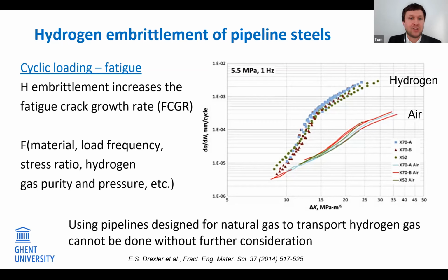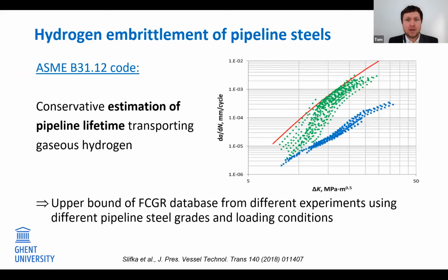Well, using pipelines designed for natural gas, which are used nowadays in the existing grid, to transport hydrogen gas in the future cannot be done without further consideration. The pipeline lifetime can be estimated conservatively by using the upper bound of the fatigue crack growth rate database, gathered from experiments using different pipeline steels, grades, and loading conditions. This method is proposed in a recent modification of the ASME code B31.12, concerning the fatigue lifetime of pipelines transporting gaseous hydrogen. Data of 4 pipeline steels, X52 and X70 steels, with gas pressures up to 21 megapascals are shown here in green. The equivalent fatigue crack growth rate in air is displayed in blue, and the red line represents the approximate upper bound of the data, and this is implemented in the new B31.12 code.